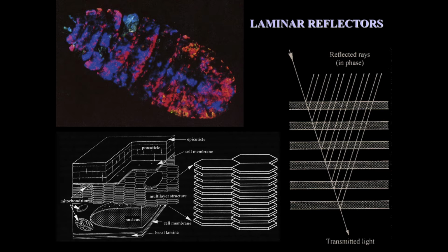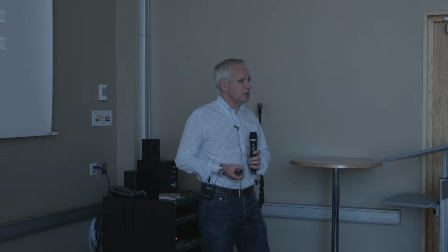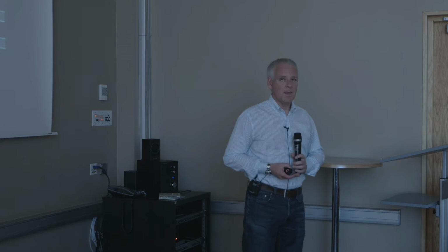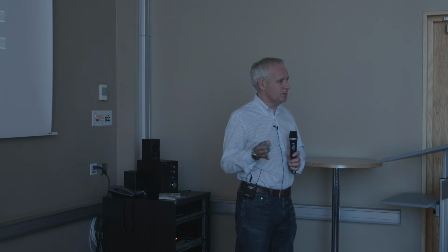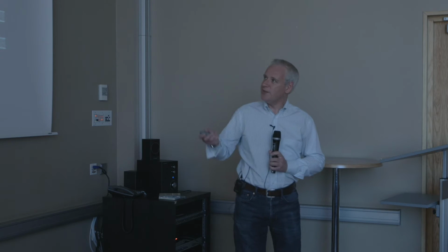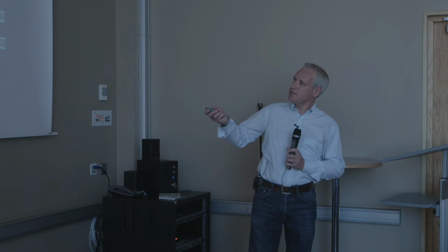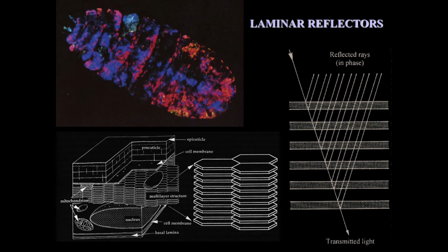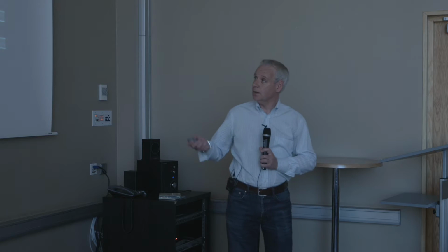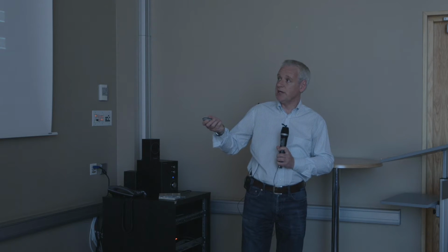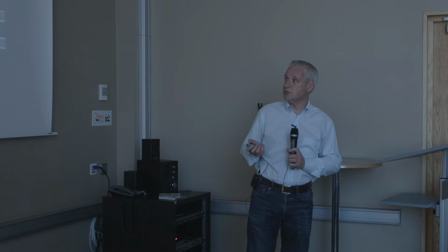But they became quite intricate in nature. This is Sapphirina, a copepod crustacean that's only about 5 millimetres long. This is a male. The female is transparent. But the male, within its cells, has this nice stack of hexagonal platelets interlocking. These are made of guanine, with a refractive index of about 1.83, working essentially in cytoplasm, which is about 1.333.